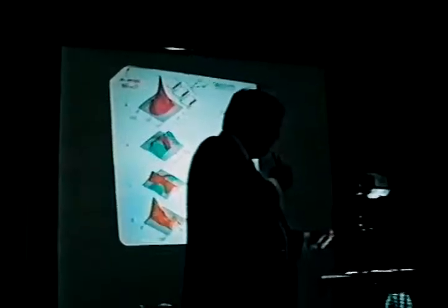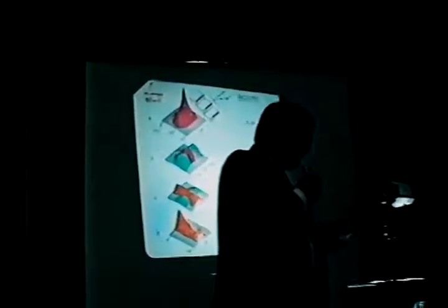And this particular pattern is only observing molecules on the step. It turns out that the terrace molecules, which also fill in the backside of this pattern, are not shown here for the purposes of this talk. So we have evidence then that orthogonal tilt directions take place as the local crowding of molecules on these one-dimensional arrays of COs increases in the experiment.